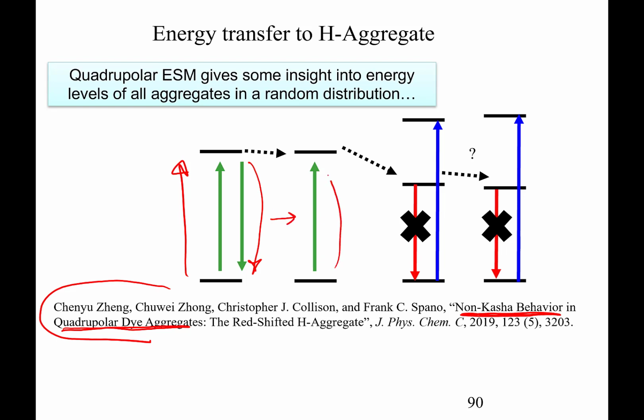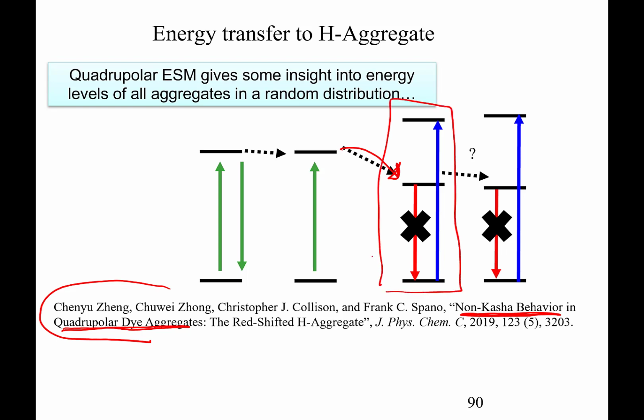What happens is when these monomers start to interact or eventually find another aggregate right next to them, there's an energy transfer that we expect into that dark state of the H aggregate. But this transition, because there's no fluorescence allowed, is very unusual. There's also some unusual behavior associated with these Squaraines that are described fairly well in this paper, again from 2019.